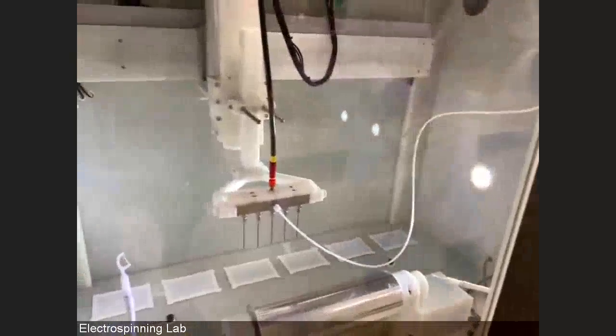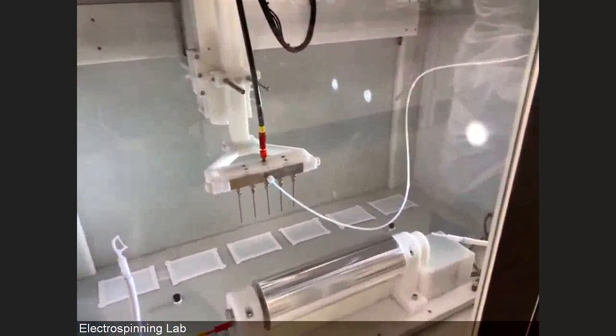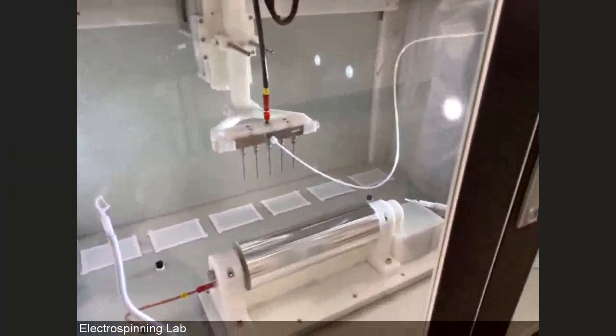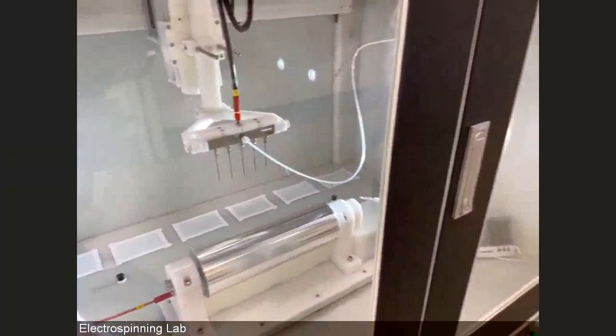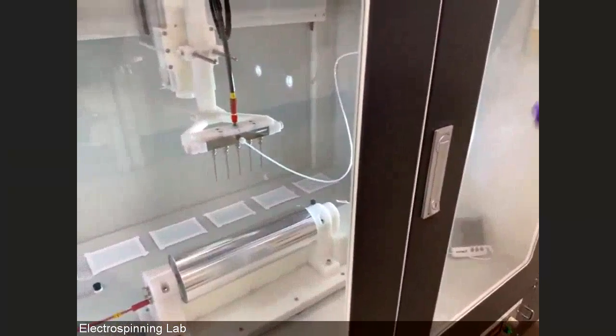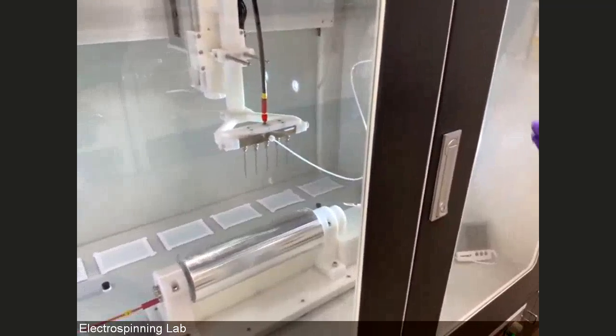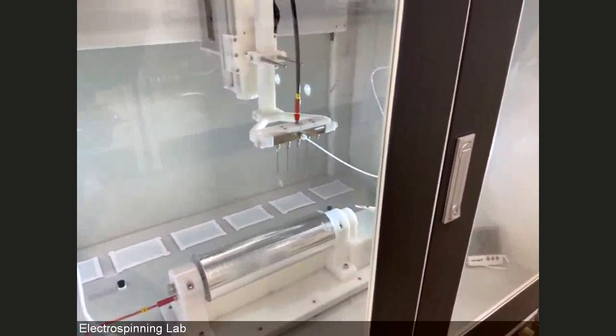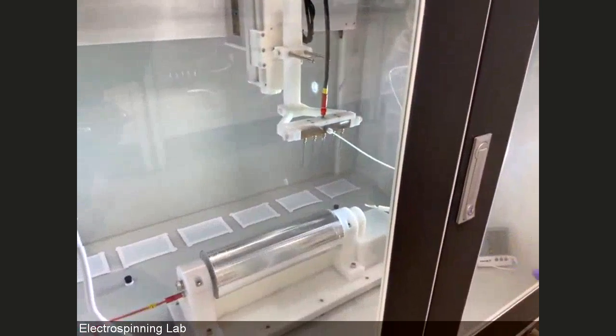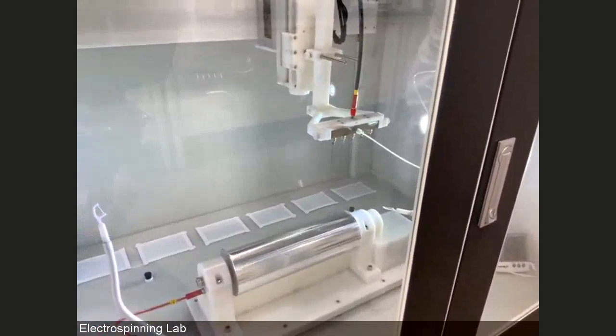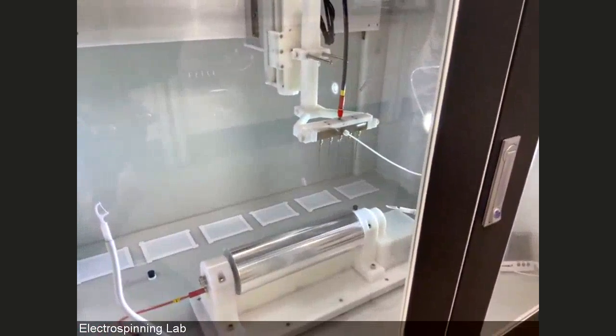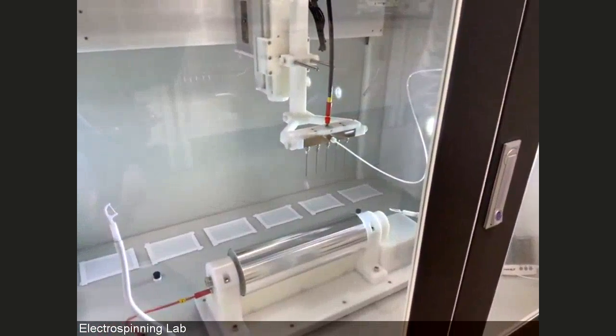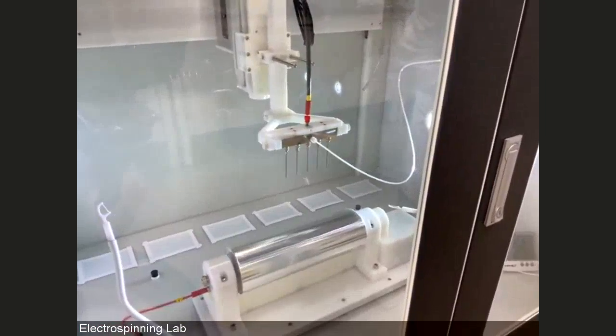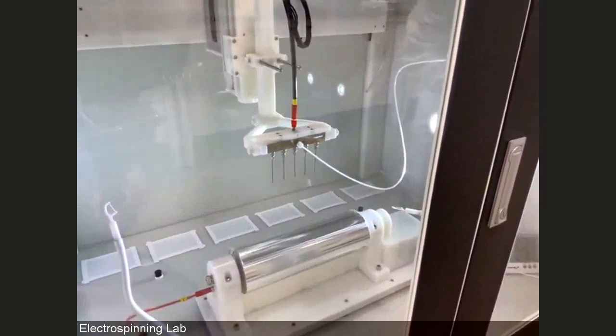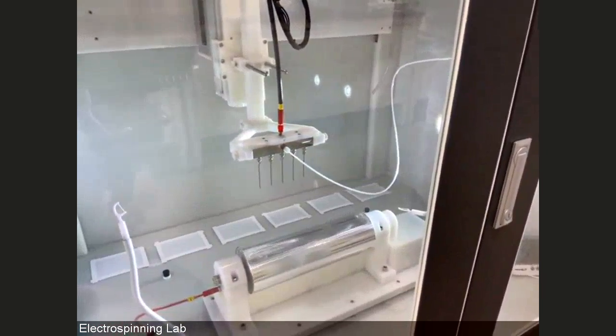So you can see that in this setup, we have the long tubing to introduce the solution to the nozzle. And the nozzles here we use are just regular metal needles, and we have five of them right now. On the other side, we have a rotating drum. That is the collector that can continuously collect the fibers during the experiments. And we can move the needles left and right to generate some patterns if necessary.